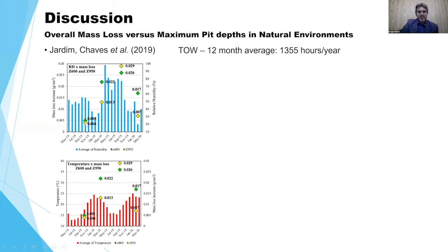The green and yellow dots are an average mass loss for different types of materials. In this case, just the galvanized. So a Z600 is a 300 grams per square meter of, so less galvanizing, let's just call it that way to keep it simple, and the more galvanizing, yeah, hot dipped. So as you can see, sometimes there's no difference between how much zinc you put on it early on, but then it increases and then it drops again and then increases.